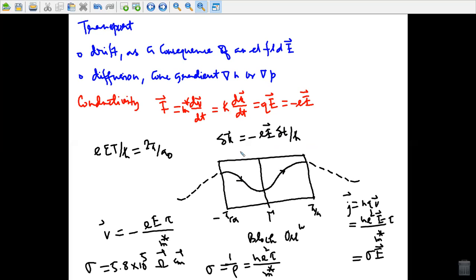Each such motion is called a Bloch oscillation. However, in a bulk crystal, the period T of such an oscillation is ħ divided by eEa, that is 2π by a0, which is of the order of 10 to the power minus 10 second for an electric field E equal to 10 to the power 4 volt per centimeter. This time is much longer than a typical scattering time, which is 10 to the power minus 14 second or so. Thus, in bulk material, the Bloch electron cannot reach the zone boundary. This is the dotted curve.